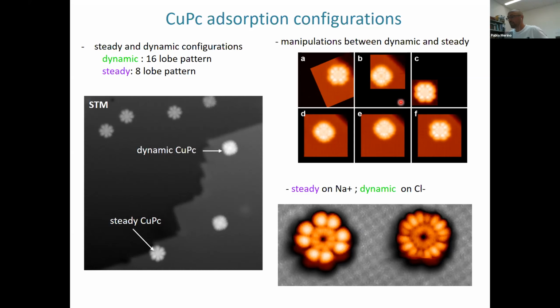And the difference between copper and zinc for the adsorption configuration is that in this case, while the dynamic molecule is sitting on chlorine atoms, the steady configuration is sitting on sodium atoms. And we can see here that in this case, the purple lines are on top of the brighter regions and the green lines are on top of the darker regions of the lattice.